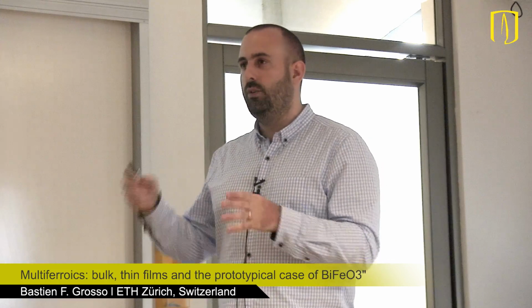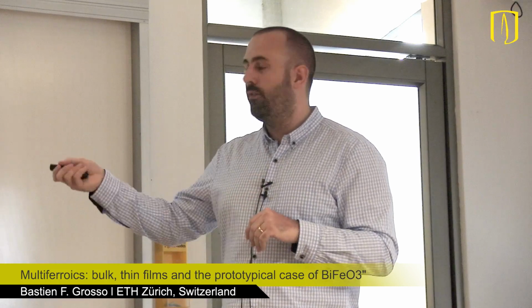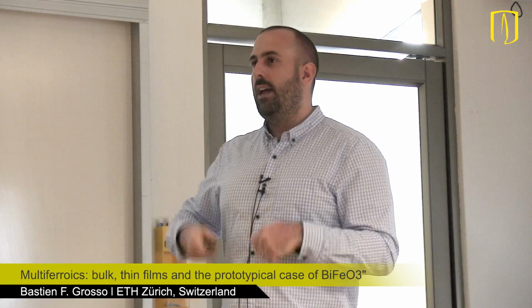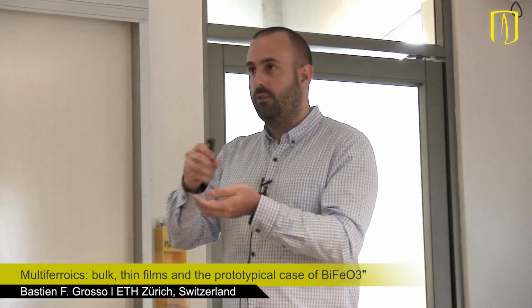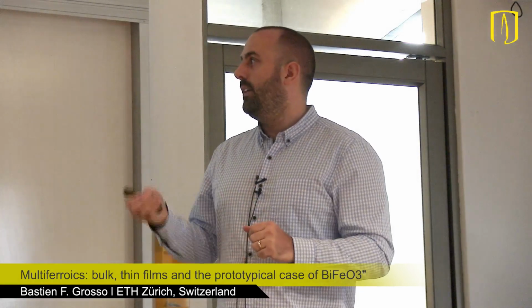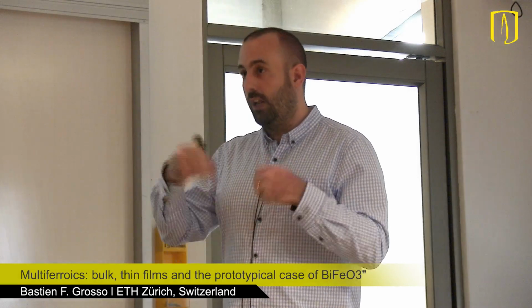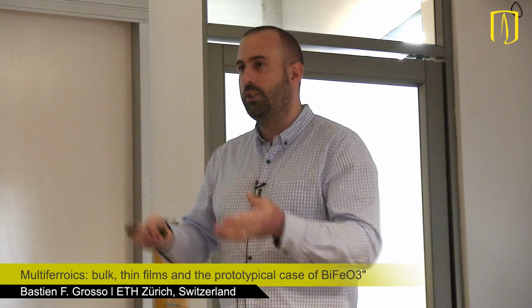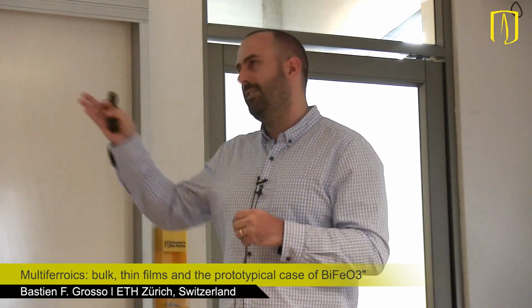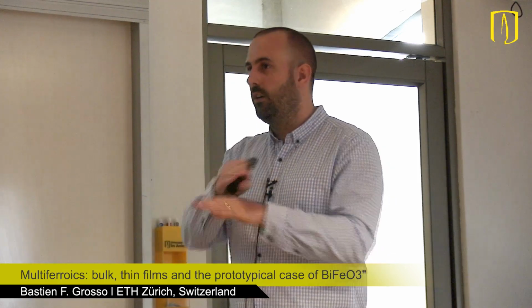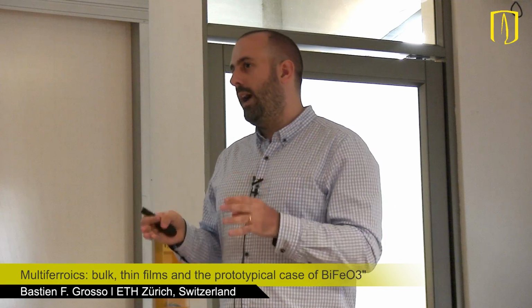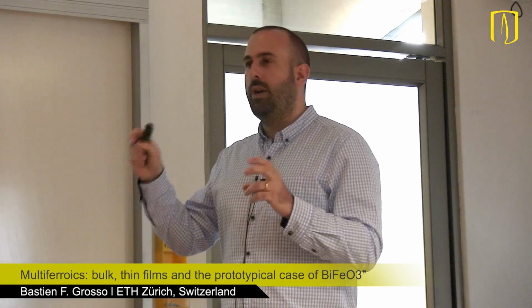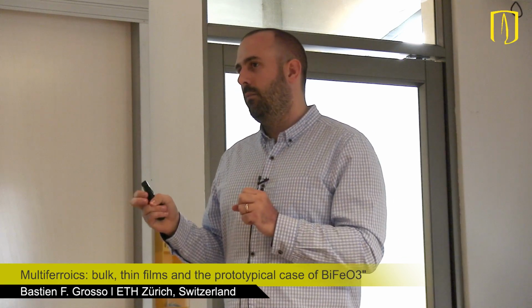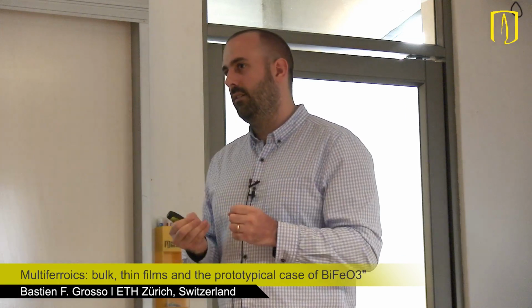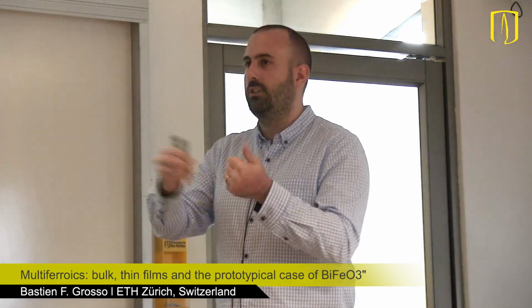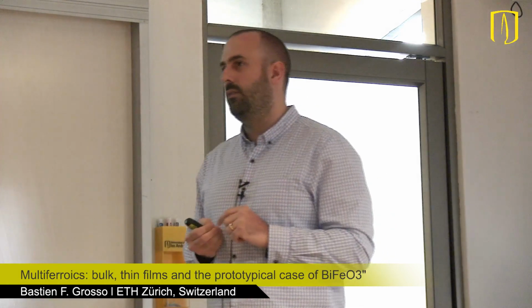And what they observed is that doing that, you see coexistence of antiferroelectric and ferroelectric phase. And you can also change the material surrounding on the same substrates always. And they tried with strontium titanate, which has a large dielectric constant, meaning a low energy cost to screen. And in that case, it stays ferroelectric, polar, in the whole film. Which is why also we think that strain is one of the ingredients, but the main one is the electrostatic. Because controlling electrostatic, you can change the behavior.